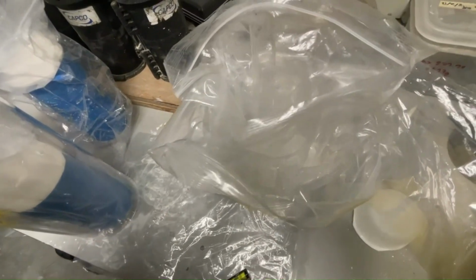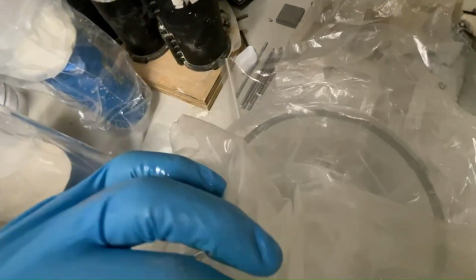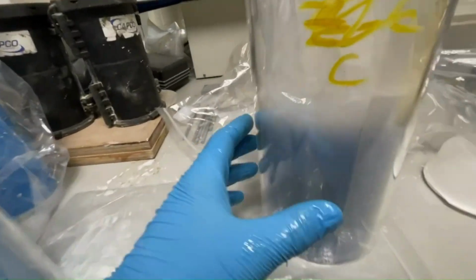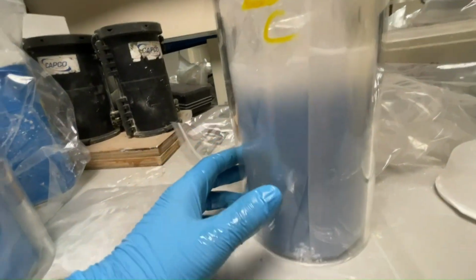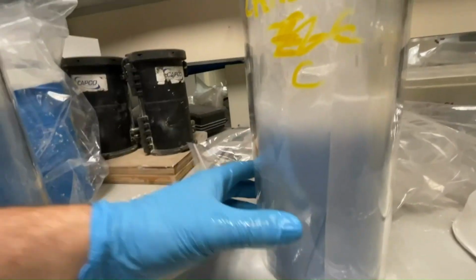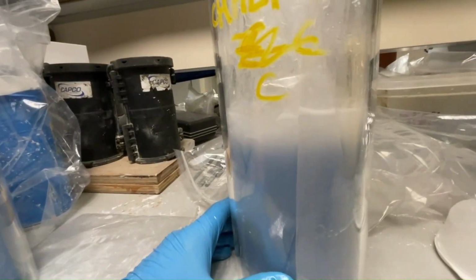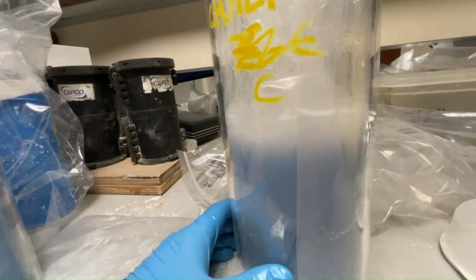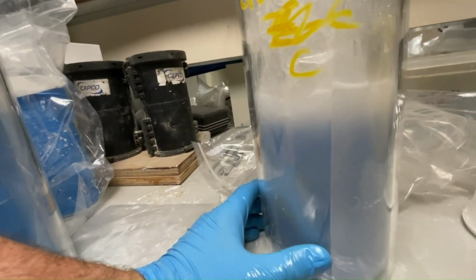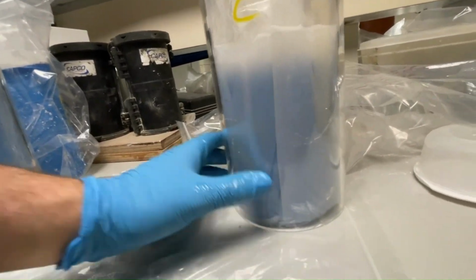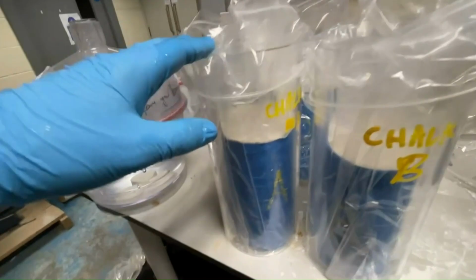So we can leave this sample now to cure for around 5 days. I'll come back periodically over the next couple of hours just to check the level of the resin. If it drops down too much, goes below the sample, add a little bit more. But usually if there's significant volume changes, that's indicating that there's potentially been something up with your mix proportions. So just bear that in mind. Otherwise, I'm happy with the sample, and I'm going to move on to the next two.